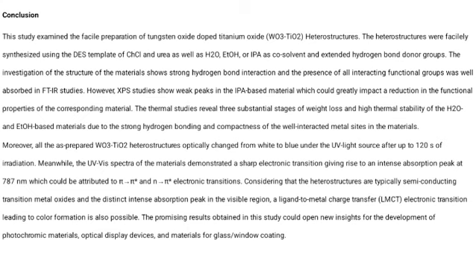Considering that the heterostructures are typically semiconducting transition metal oxides and the distinct intense absorption peak in the visible region, a ligand-to-metal charge transfer electronic transition leading to color formation is also possible. The promising results obtained in this study could open new insights for the development of photochromic materials, optical display devices, and materials for glass, window, and door coating.